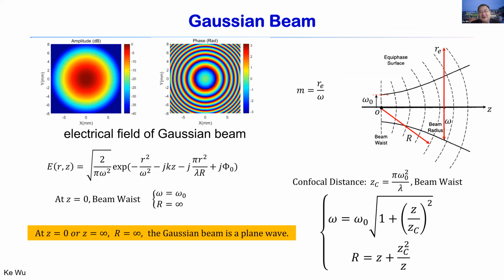And also regarding Gaussian beam design, of course, this is well known in the optical domain, but in the quasi-optic field, one of the most important things is that over large frequency bands, you have to create a very high efficiency Gaussian beam generation. Particularly, we have to pay attention to the beam waist regions. So this is a formula for how the beam evolves with distance, as the point of observation goes away from the original point, which is where the beam waist omega 0 is located. The beam expansion or beam width enlargement can be formulated by this formula as a function of the point of observation. ZC is the confocal distance point.